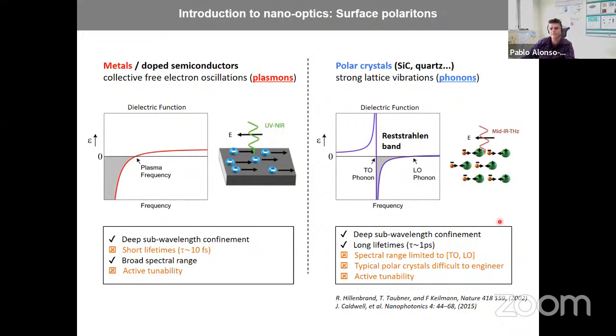And by screening out this incident field, it creates this surface wave on the material that has the same properties as surface plasmons, such as strong confinement and so on. But instead of having such short lifetimes of 10 femtoseconds, in this case, because the main loss mechanism in phonons is phonon-phonon scattering, the lifetimes are in the picosecond range. The phonon polaritons that are excited have more or less this lifetime, picoseconds. This is key for applications where you want to control light-matter interaction and you want it to be enhanced, right?